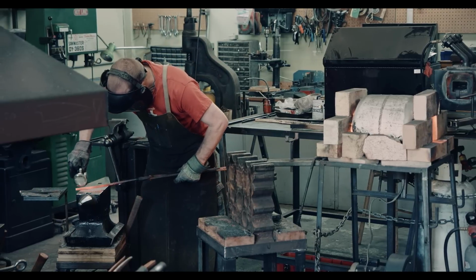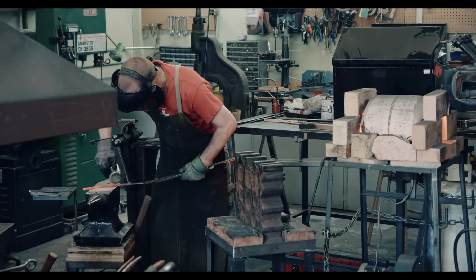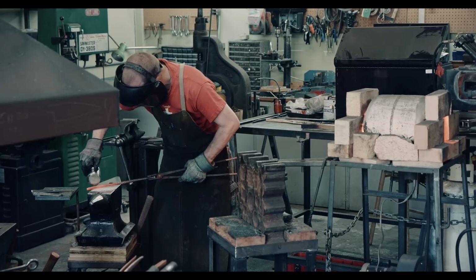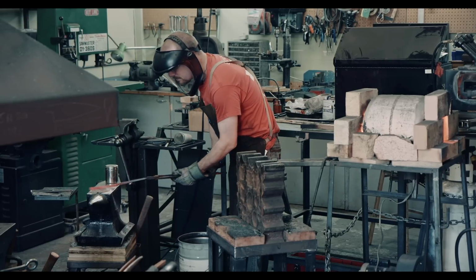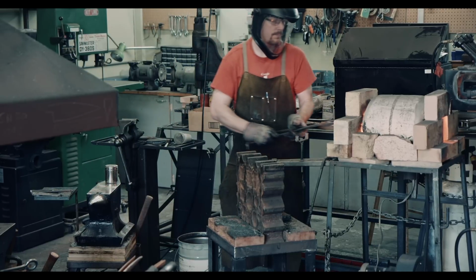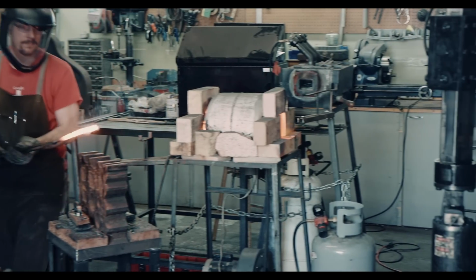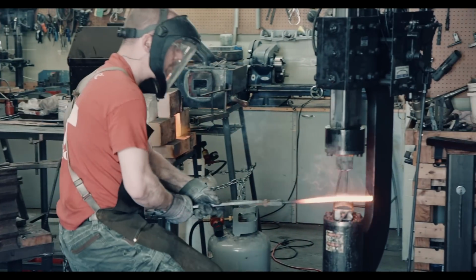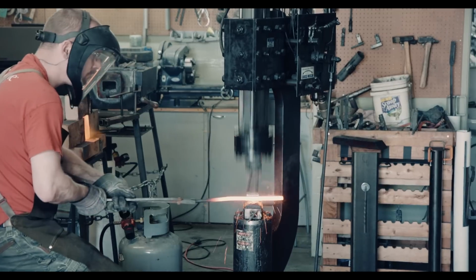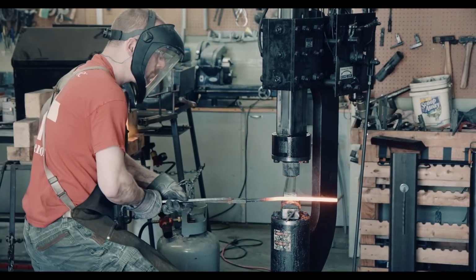After twisting, the bars always need to be forge welded back to square before they can be used any further. As with all my forge welding, I do this in sections and make sure that the bars are hot enough for liquid flux to squeeze out easily. To maintain the same dimension, I use a spacer on the power hammer.